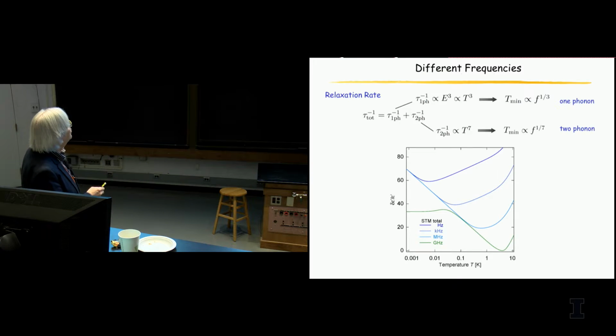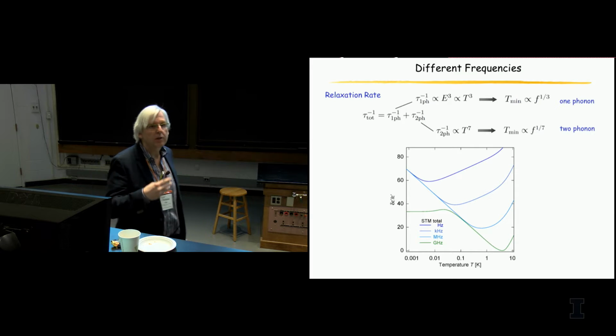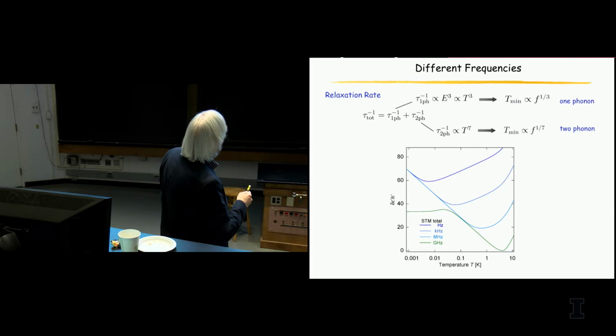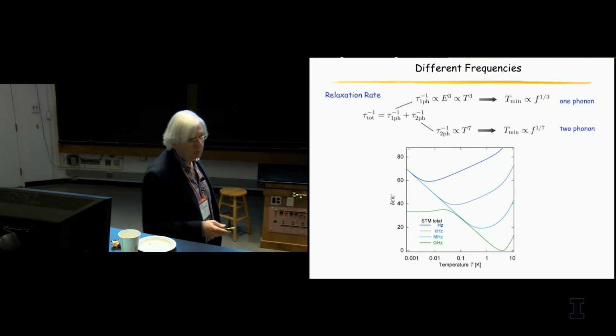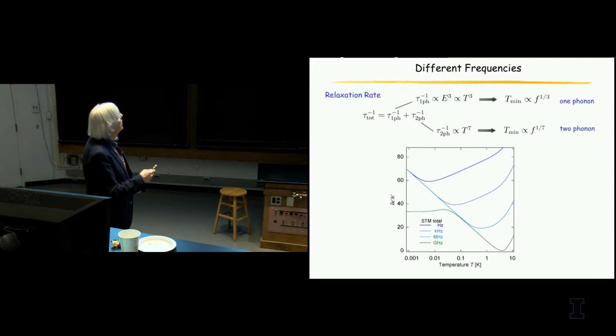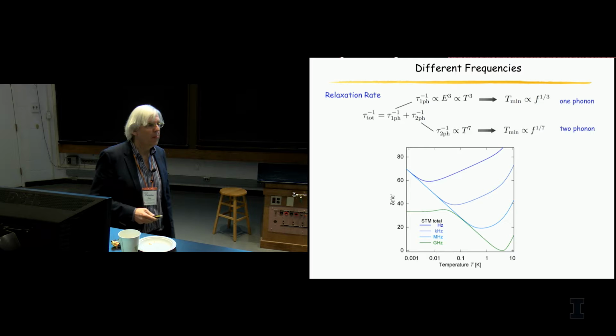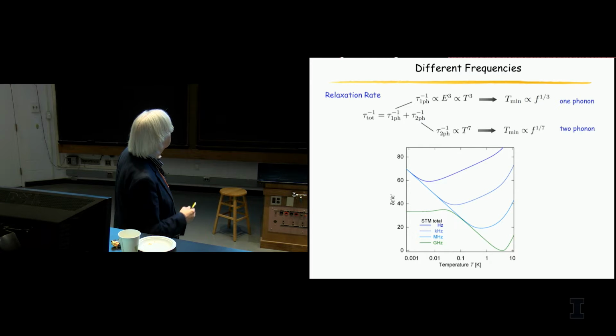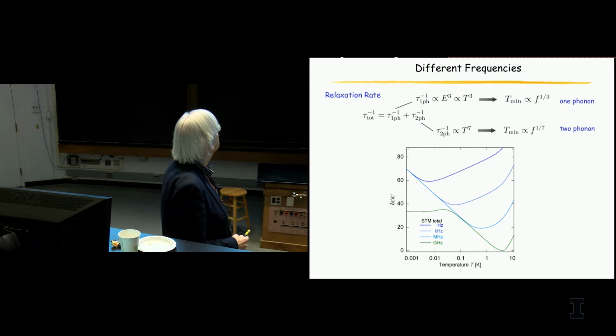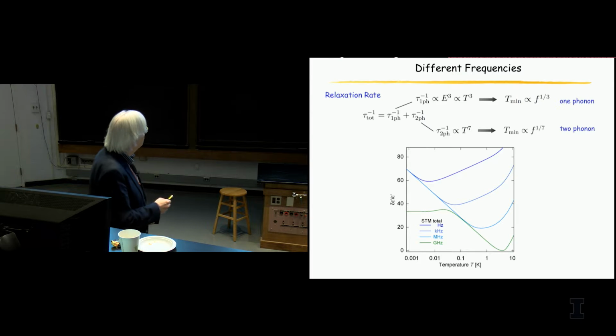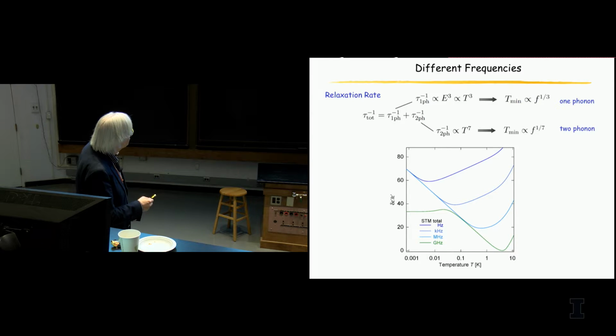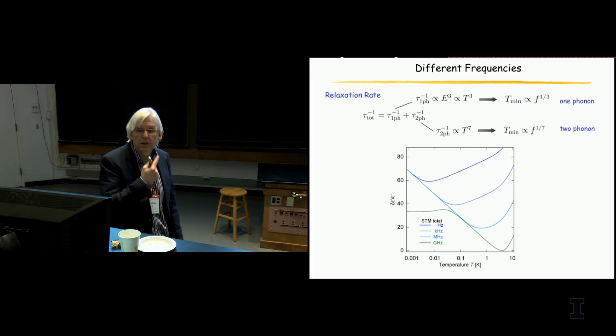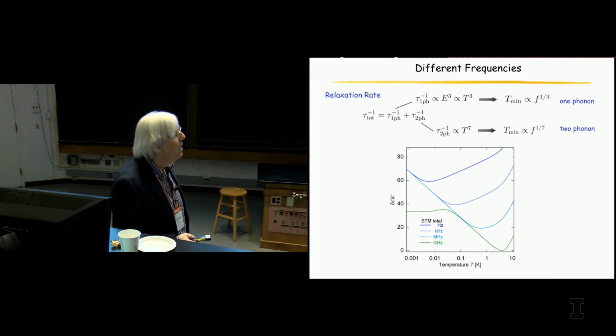Now, you can then do this at different frequencies. These are all calculations. This minimum shifts with frequency to higher temperatures. And the way it shifts depends on the dynamics the system is doing. So the minimum shifts with omega to the power of 1/3 if you have the one phonon process. If you have a higher order phonon process, it shifts with the power of 1/7. So you can see here this already becomes sharper because the two phonon process sets in at those high temperatures.